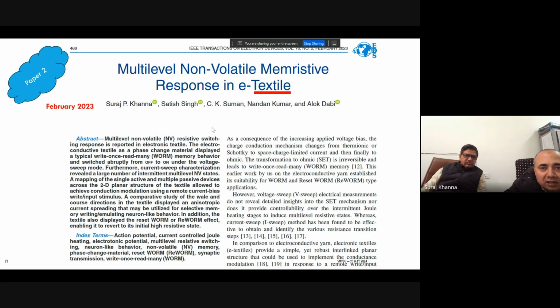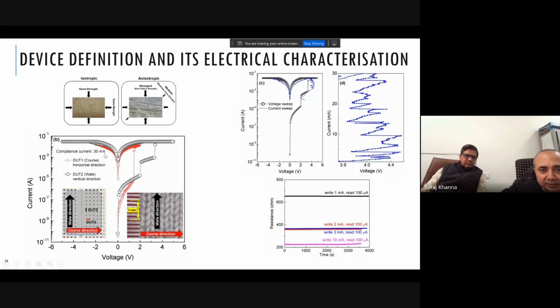Okay, so now we move to a fabric. The same yarn, when knitted into a fabric, typically shows similar behavior to what was seen for the yarn. But here we found one more thing: when, instead of applying voltage directly, you apply current, then you can see multiple states between the highest resistive and lowest resistive state. These are the additional states which we were able to record or visualize because we were now applying current.